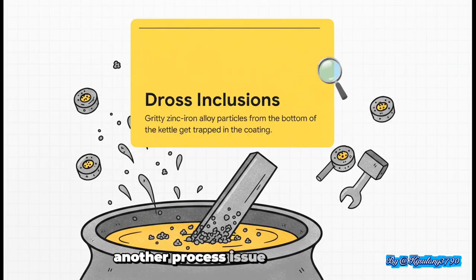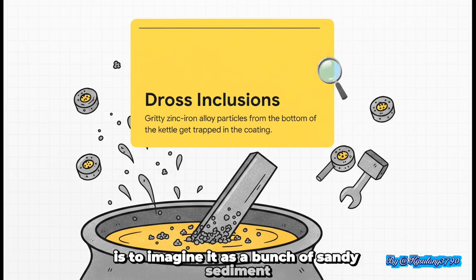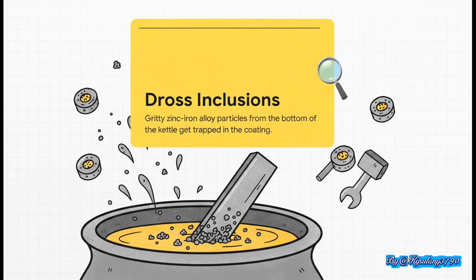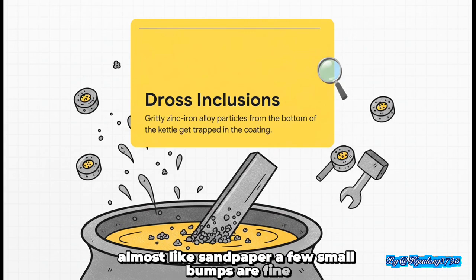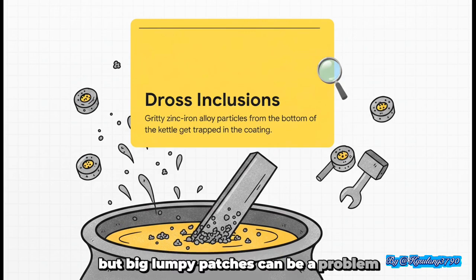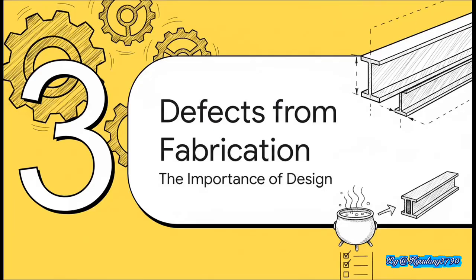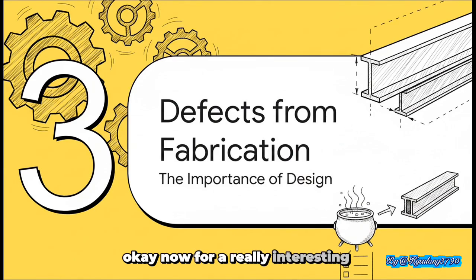Another process issue is something called dross inclusions. Now, the easiest way to think about dross is to imagine it as a bunch of sandy sediment that settles at the bottom of the zinc kettle. If a part gets dipped too deep or the zinc gets stirred up, these gritty little particles can get stuck in the coating, making it feel rough, almost like sandpaper. A few small bumps are fine, but big, lumpy patches can be a problem and will need to be smoothed out.